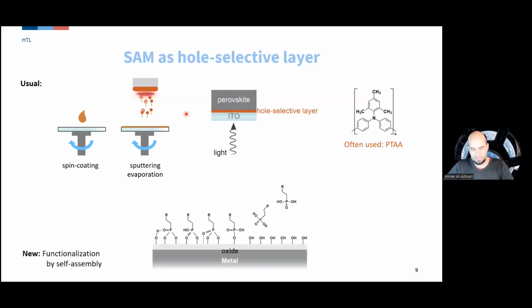And the nice thing about self-assembled monolayers is that everything happens by itself, right? So the beauty of it is you encode the function of the complete layer in the design of the molecule. And here, especially with phosphonic acids, when they see OH groups on the surface, they react to form water in different modes of binding. And you get the same layer really reproducibly, and you can be sure there's usually, if everything is done right, one layer.